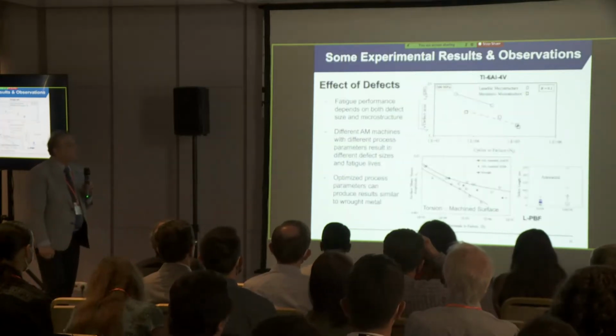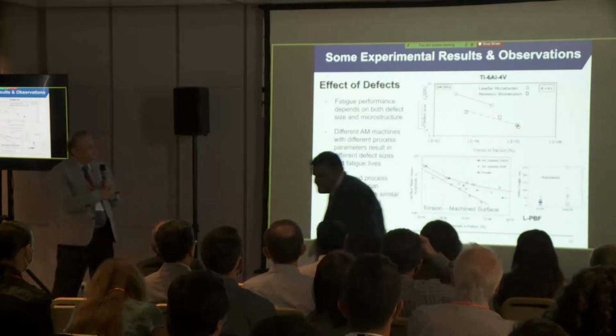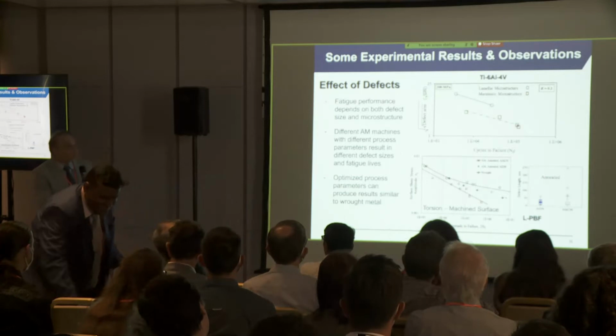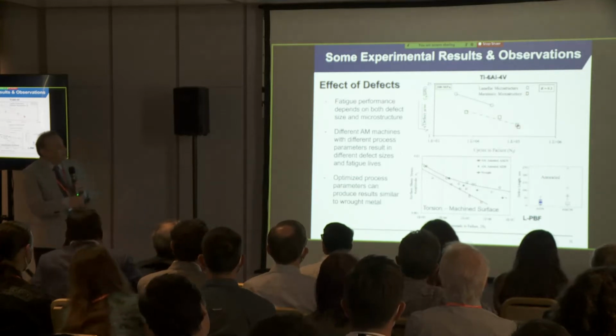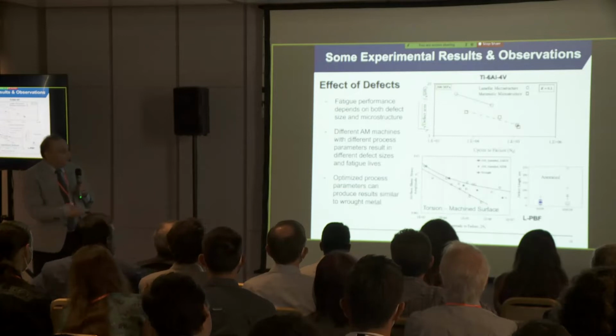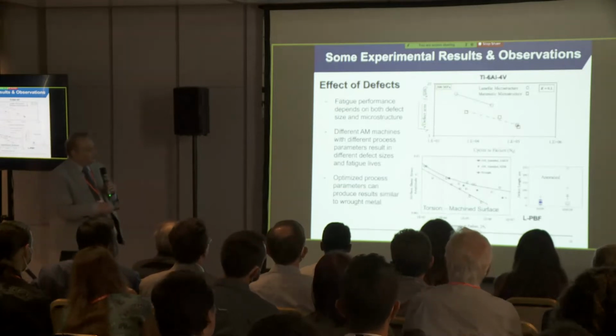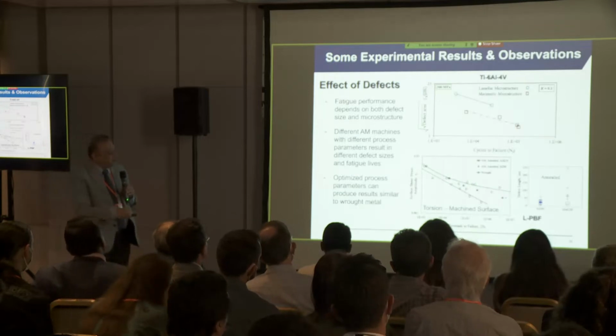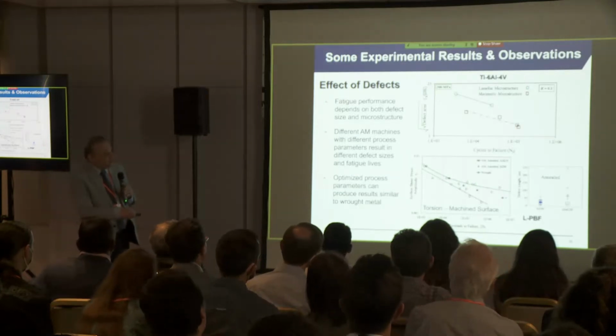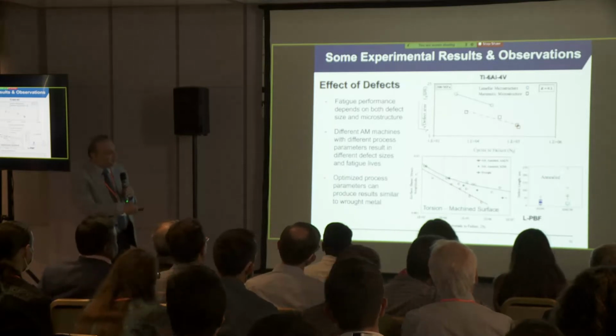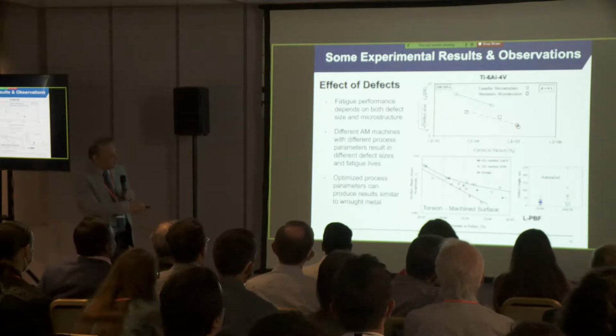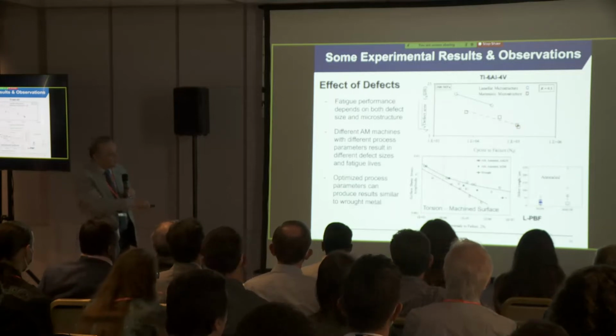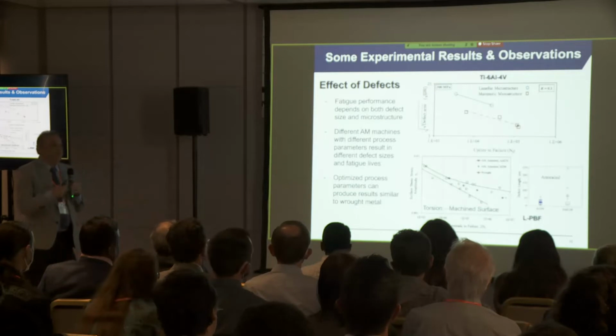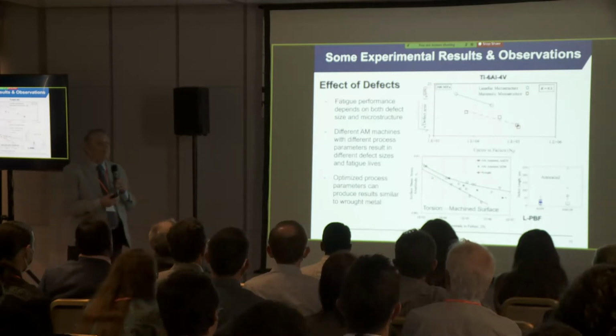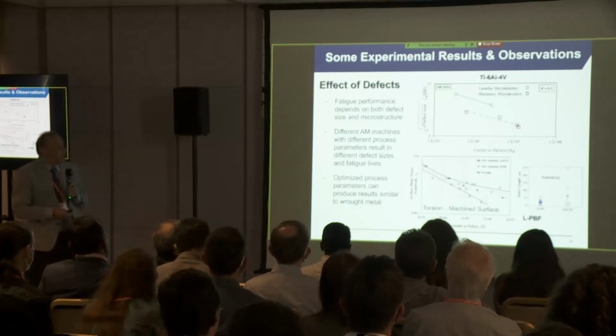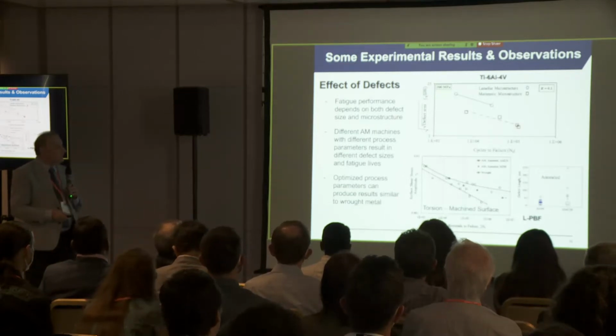So let me share with you some experimental data. In terms of defects, as I mentioned earlier, there is a big improvement in fatigue life if you can make the size of defects smaller. If you look at some Ti-64 data in torsion, this is data from one additive manufacturing machine and then another additive manufacturing machine where the defects are much smaller compared to this one. You see a big difference. And this is the wrought metal. So you can get close to the wrought metal if the machine that you use for additive manufacturing of a specimen or a component has much better optimized performance parameters.